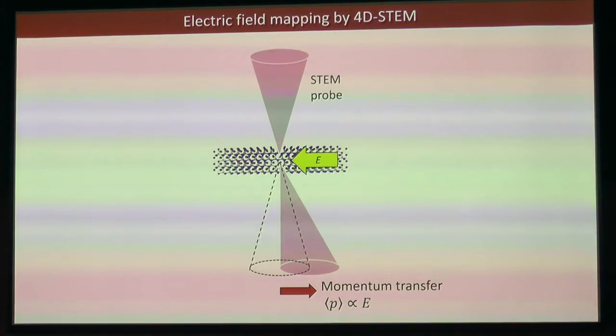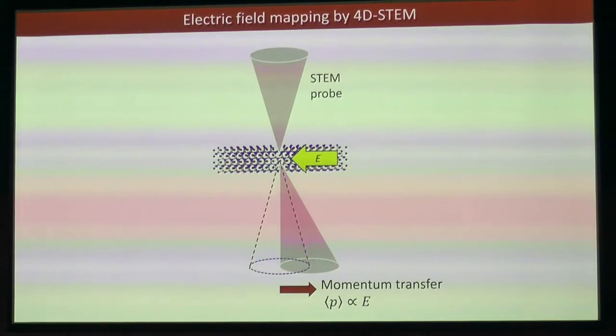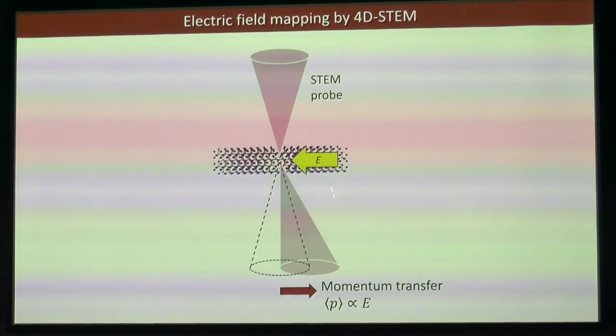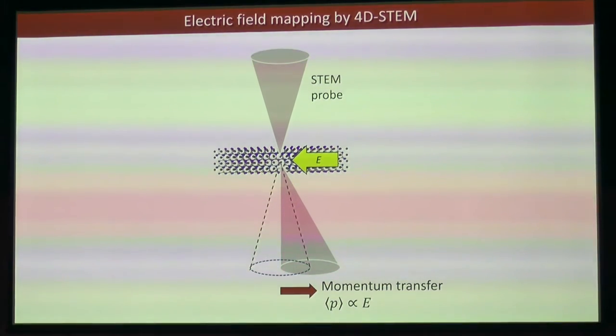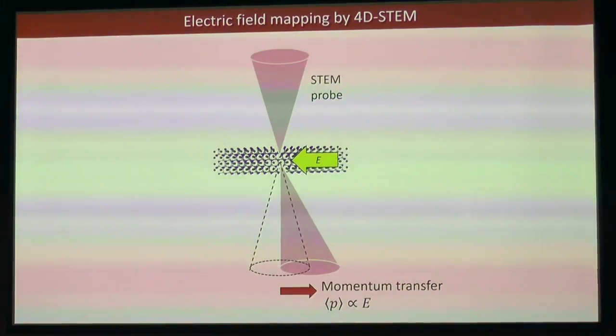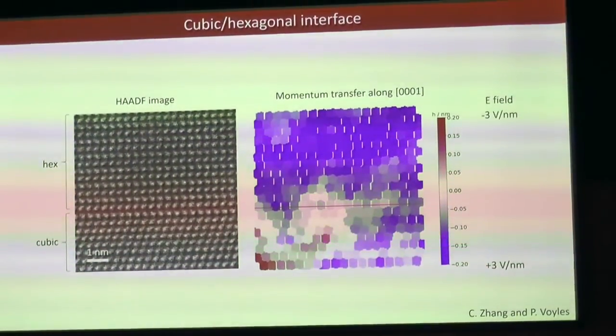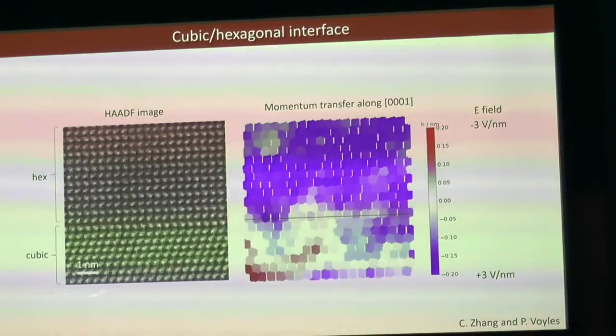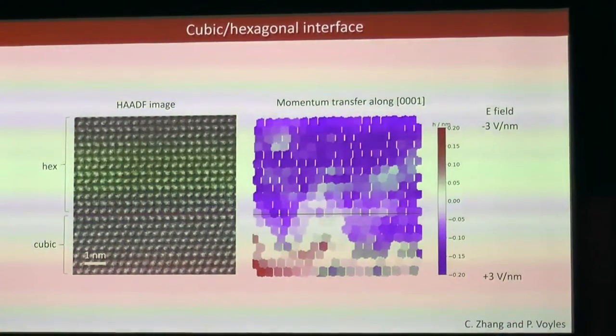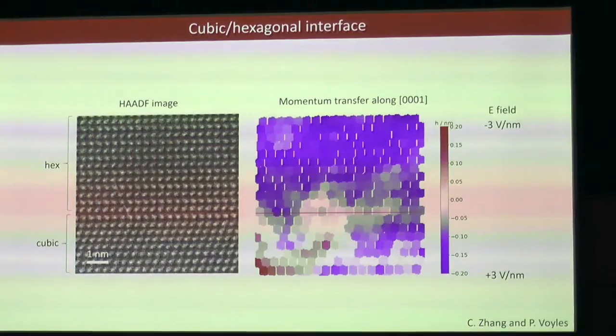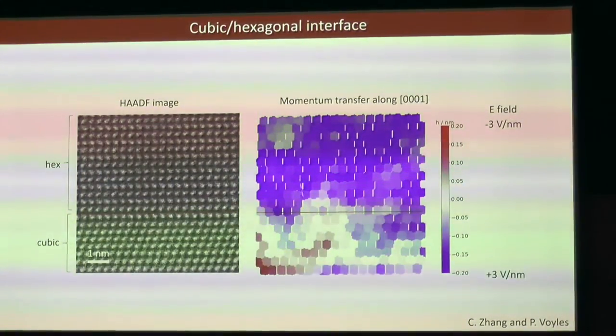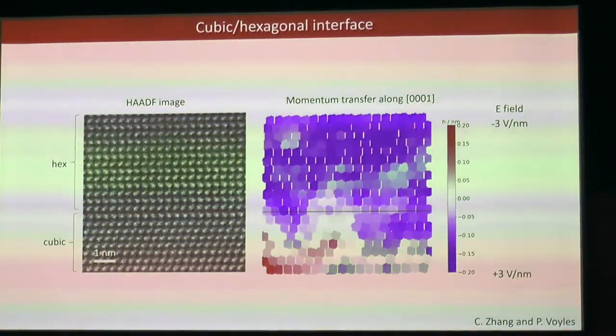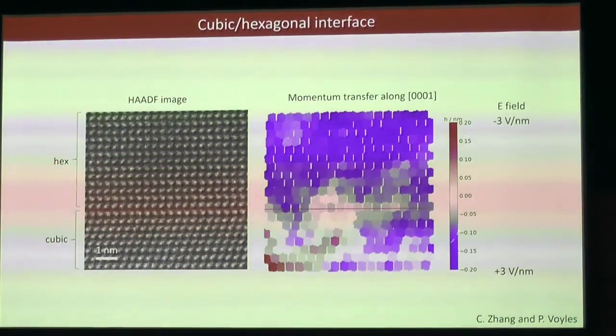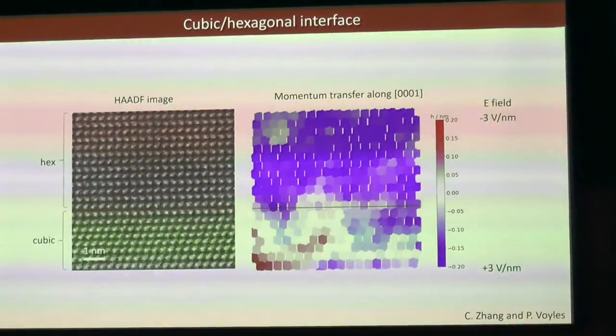So the basic idea is this lets us map out electric fields, right? If there's an internal electric field, there will be some sort of momentum transfer on the measured beam. That'll be proportional to the electric field inside the sample. So just as a first test of this, we've measured this mixed phase hexagonal and cubic lithium zinc antimony. This is the STEM image. This is the momentum transfer. The color scale is proportional to the momentum transfer. We can convert that into electric field units if we know the thickness well enough.